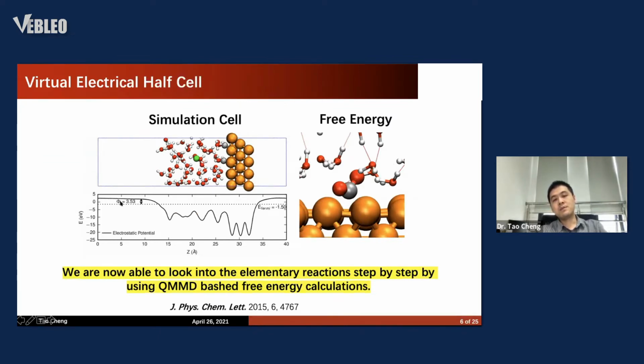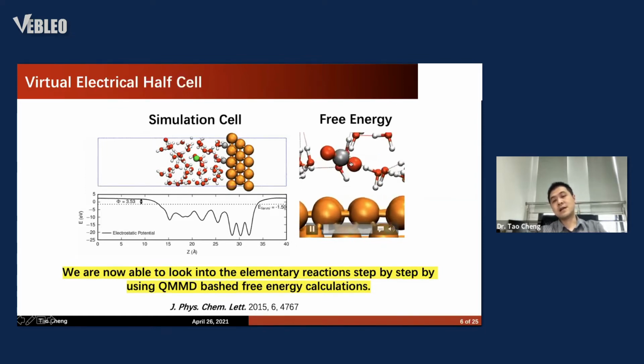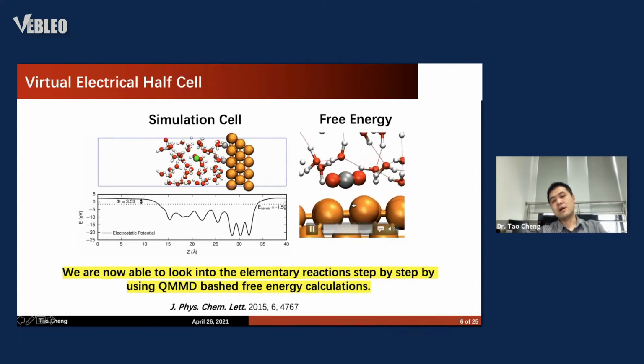To make it possible to simulate the electrochemical reaction, the central technique here is that we can regulate the work function to match the applied voltage. And with all these techniques, we can now see chemical reactions. I show one case here, where you can have a stable CO2 activated by the copper surface to have chemisorbed CO2 on the copper surface.